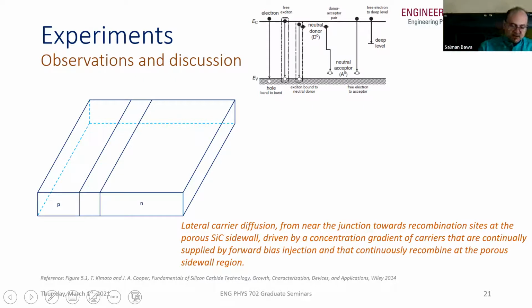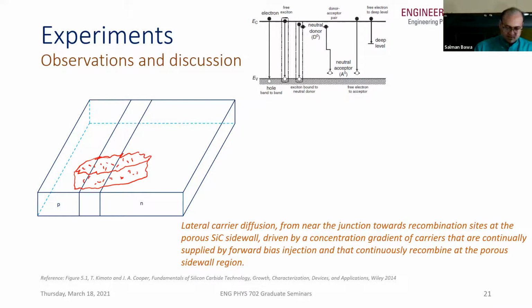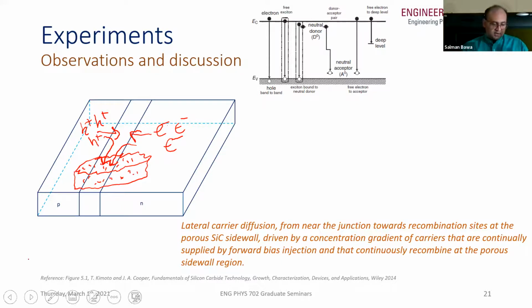But then we try to create a defect at the PN junction. And I'm just going to sketch this defect that we create. So let's say we cut this. And obviously the defect will have a depth. So we create this defect by cutting, and then we etch the junction. So these dots represent the etch. And what happens is that we have holes and we have electrons. And as they move to the PN junction, what we are saying is that they would preferentially diffuse to these defect centers that we have created and radiatively recombine there, causing now a more greenish tint to the light.